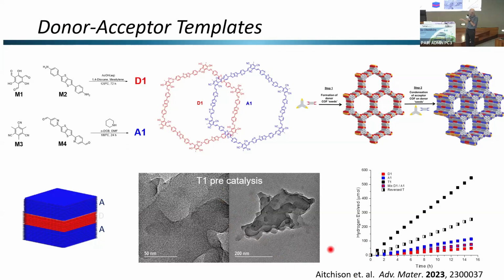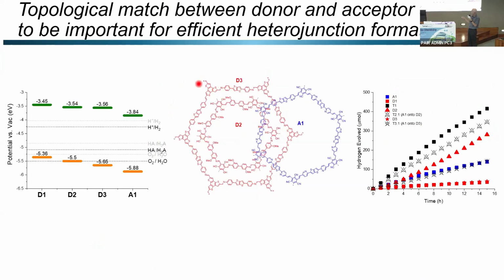We worked on templating donor-acceptor COFs together. This is work by Kath Aitchison, who's now in Linköping. You can see we make this acceptor-donor-acceptor sandwich. It actually took a lot of work to be able to do this. You start with your donor template, and it only really works when you've got a topological match between the donor and the acceptor. What that means is that the ring size has to be exactly the same. Otherwise, you get no free volume. You've just closed the pores down. And when you have this topological match, we are able to drive our chemistry quite nicely here.